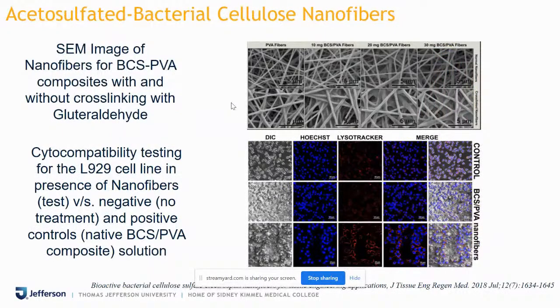But the next example that I'm going to show you is where we developed nanofibers for regenerative medicine. Here, this is an example of cellulose, which comes from a polysaccharide, and there are different types of polysaccharides that are available and being explored by various research groups. Cellulose is one of them. It's the cheapest source that was available, but we focused on bacterial cellulose because it was easy to grow the bacteria to get this cellulose, and then we sulfated this cellulose to create bacterial cellulose sulfate. This bacterial cellulose sulfate was water soluble, whereas cellulose itself is not water soluble.